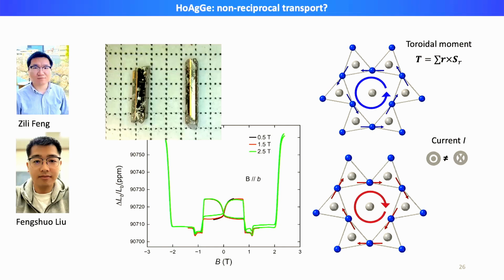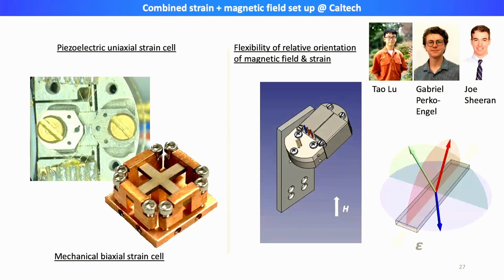So we've shown recently that we are able to use a moderate in-plane magnetic field to actually polarize the system into one of the two domains. And you can see here from this length of the sample as a function of magnetic field, where this hysteresis near the zero field is actually showing that the system is in one of the domains. So we are still in the process of trying to assess how large this symmetry-allowed non-reciprocal transport would be, and if we can really capture this, I think it would be a really cool physical response that's a result from magnetic frustration.